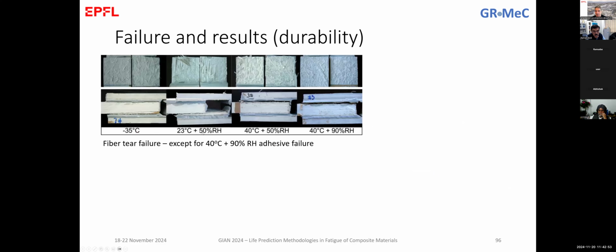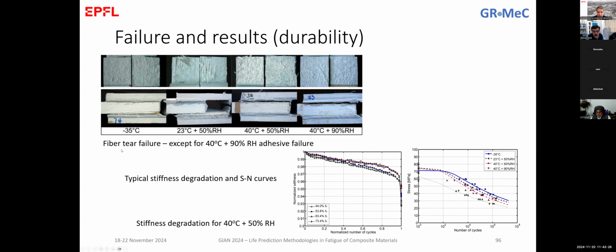So we did also durability analysis, which means that we did again fatigue testing, but for specimens that were preconditioned: specimens at minus 35 degrees, very cold conditions, Swiss conditions, specimens at typical laboratory conditions, 23 degrees and 50% relative humidity, and at higher temperatures but the same humidity levels, and at higher temperatures and specimens immersed in water. And we've seen quite different results.